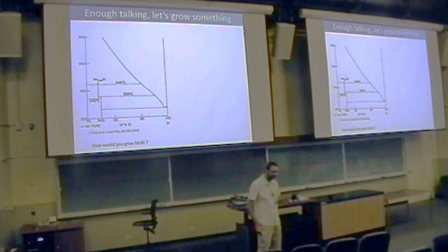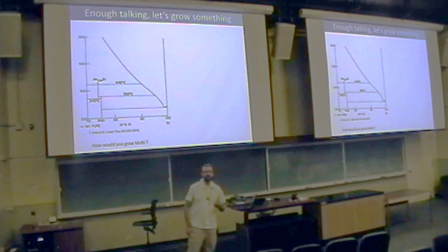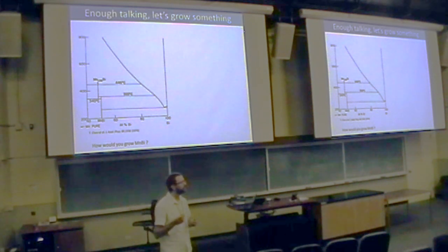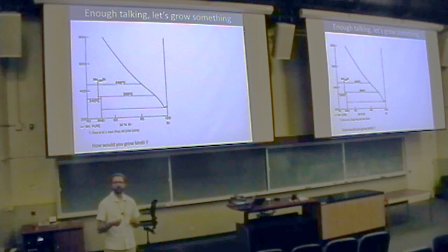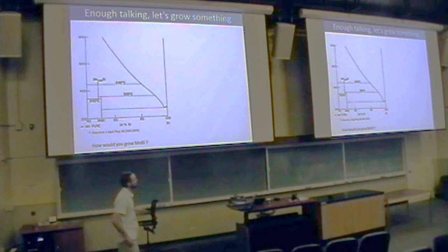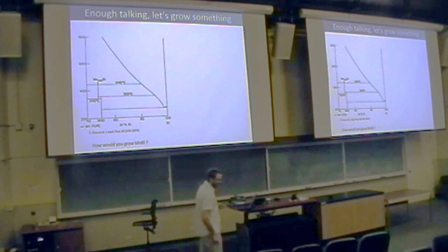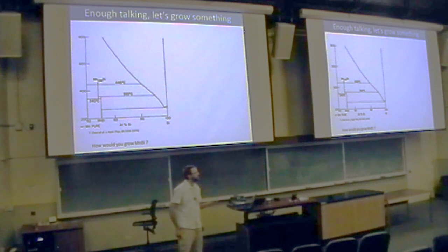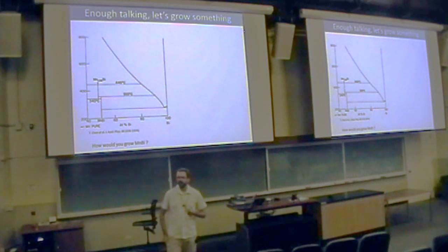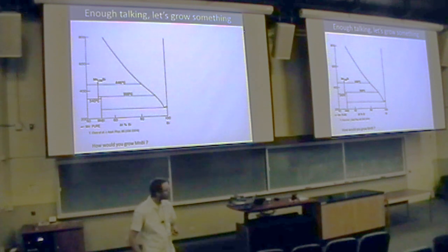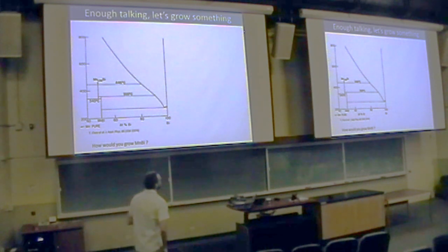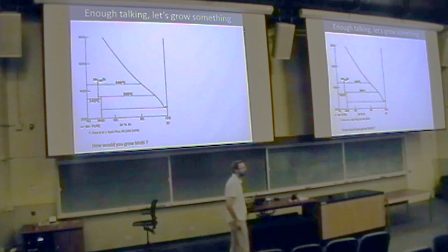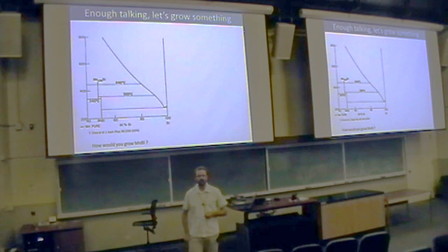But also, it is a ferromagnetic material with a very high Curie temperature. And in fact, it has something very peculiar. The magnetic anisotropy of this material increases when you increase temperature. Most compounds, the magnetic anisotropy decreases when you increase temperature, but this one, the magnetic anisotropy increases. And also, it's a very uniaxial magnetic anisotropy, and so that means that you can use this compound to make permanent magnets, for example. So let's try to see if we can figure out how to grow single crystals of this compound just by looking at this map here.